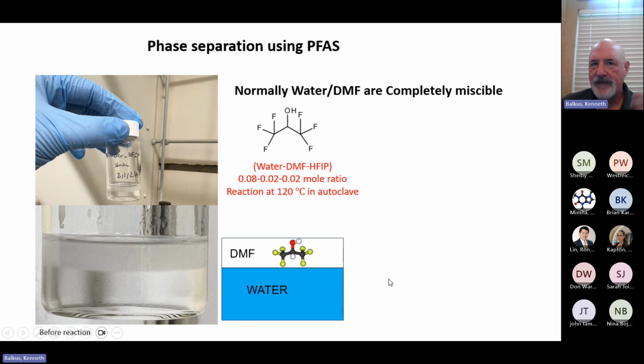Now, normally, if you take water and DMF, they're completely miscible, which is, again, part of the challenge if you're trying to develop a system by which you're going to remove and degrade the PFAS molecules. But this is interesting. If you take DMF and water, and then you add the PFAS molecule, it phase separates, okay? And the PFAS molecule actually partitions into the organic phase.